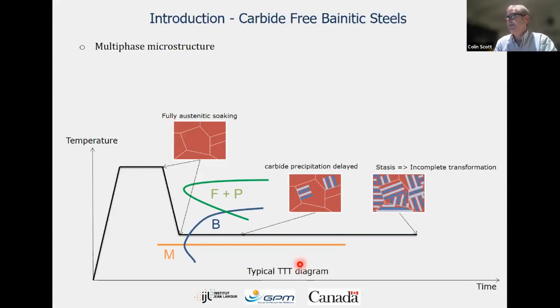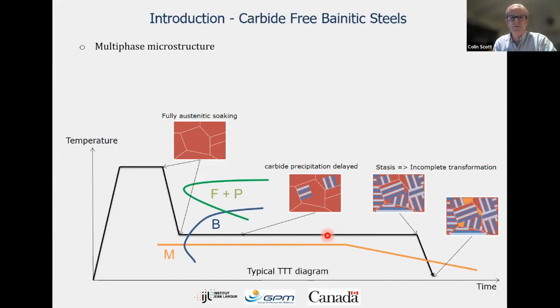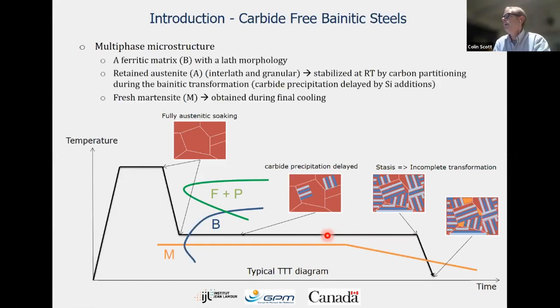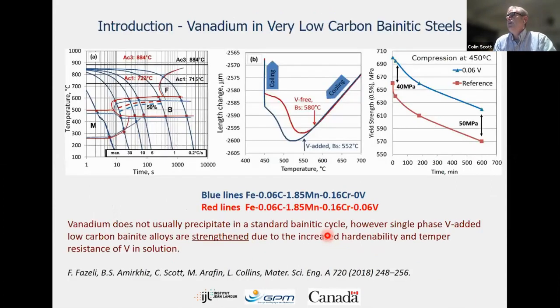And then at the end of the transformation, there's a stasis. It doesn't go to completion. So we will have some austenite that is not transformed. And as we cool down to room temperature, some of that untransformed austenite may be unstable and transform to martensite during the cooling. So we'll have essentially a 3-phase microstructure at the end. We have a bainitic ferrite, austenite, and some martensite.